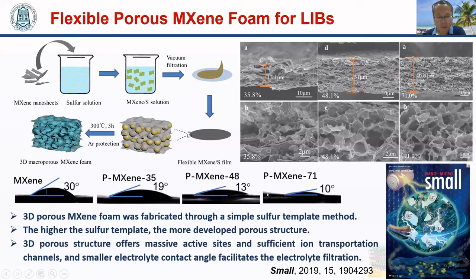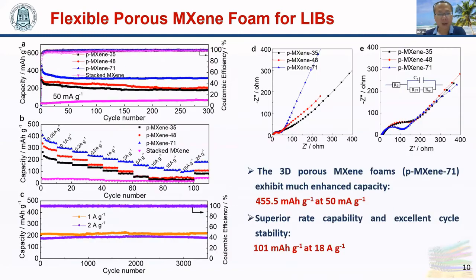The 3D porous structure offers massive active sites and sufficient ion transportation channels, and a smaller electrolyte contact angle facilitates electrolyte infiltration. The 3D porous MXene films exhibit much enhanced capacity. The capacity can reach nearly 500 mAh per gram for lithium storage. It also shows very stable cycle performance and very good rate performance. It can output 100 mAh per gram at 18 ampere per gram. This is a very large current density.